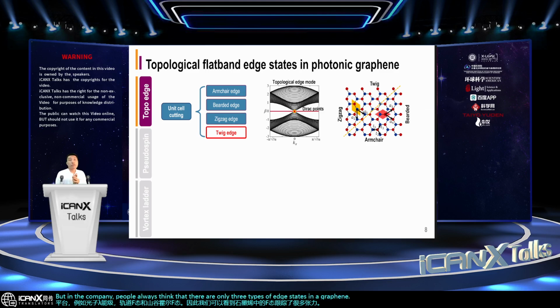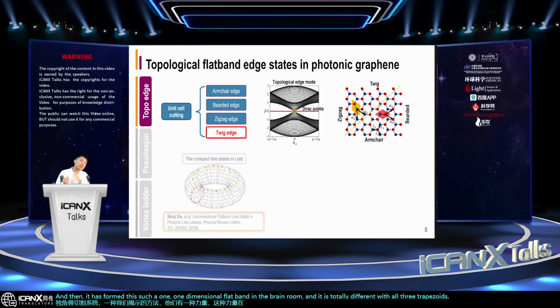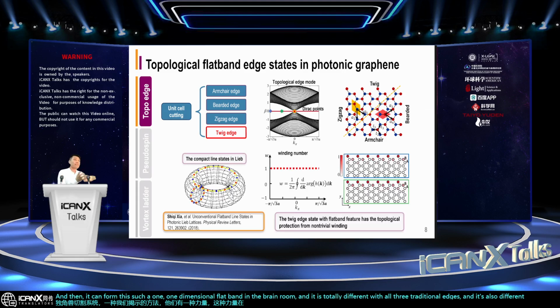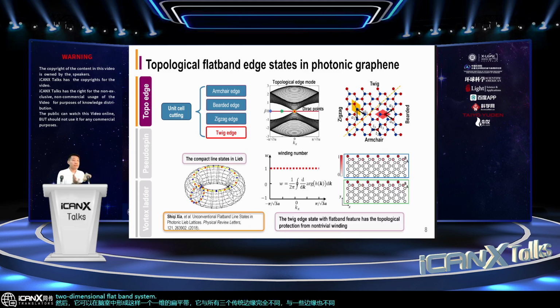graphene. But in our study, using the unit cell cutting method, we reveal there is a 4th fundamental edge state in the photonic graphene, and it can form such a one-dimensional flat band in the Brillouin zone. It's totally different from all 3 traditional edges, and it's also different from the compact lattice states in 2-dimensional flat band systems as we demonstrated before. Such edge states we refer to as the twig edge. The twig edge states have some flat band features, but also have topological protection from the non-trivial winding caused by the Dirac cones.